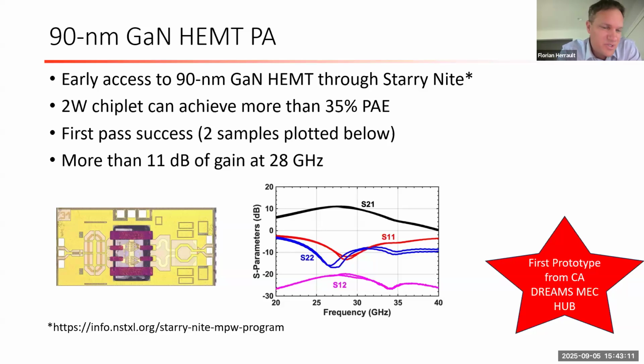The chiplets are differential designs here. It's roughly a 2-watt chiplet, and we achieved first-pass success. We just picked 2 samples here. They overlay very nicely onto each other, and that was a building block. And that was the first time we took a 90 nanometer design, chipletized it, and then integrated it into a passive silicon wafer here.